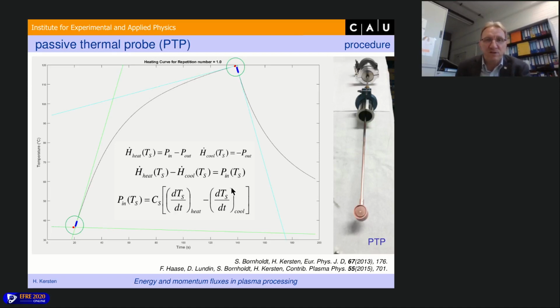And then it's very simple. It's like textbook in the first year for the students. You just have the heating of the probe and the cooling of the probe. And this is related to the time derivatives of the temperature during the heating phase and the cooling phase. You just have to have the derivatives here. Usually we take it here in the beginning of the process. And if you know the heat capacity of the probe, you have to know the heat capacity by calibration procedure, then by this simple formula, you get the integral energy flux measured by this probe. It's really very, very simple.